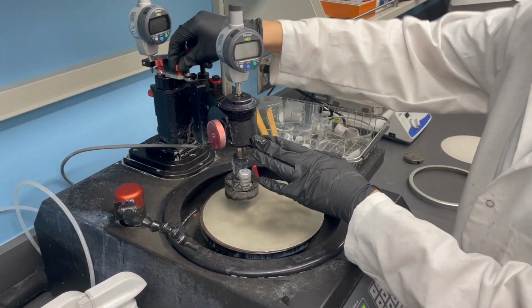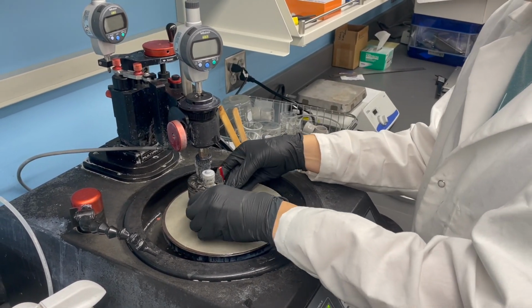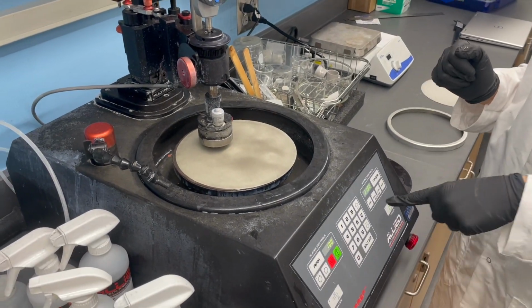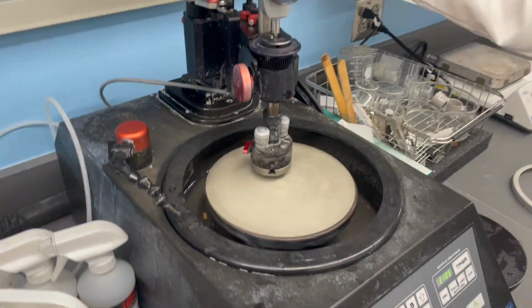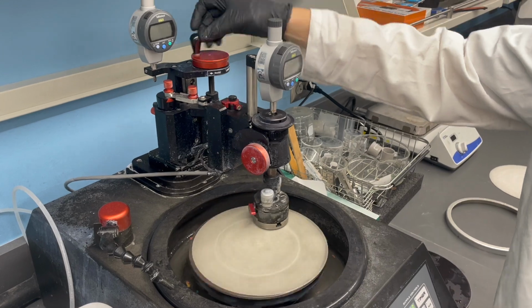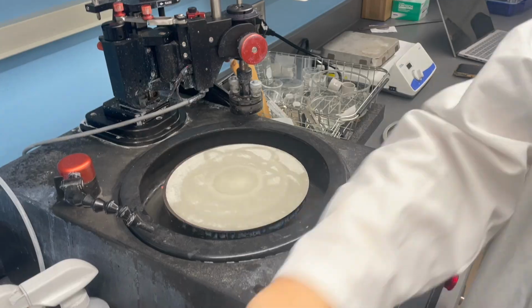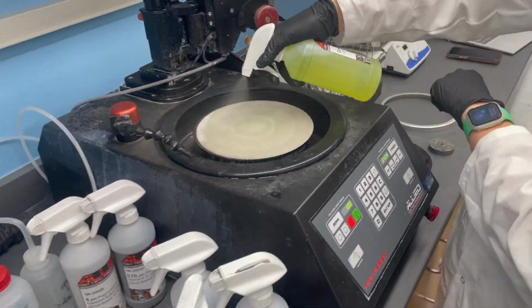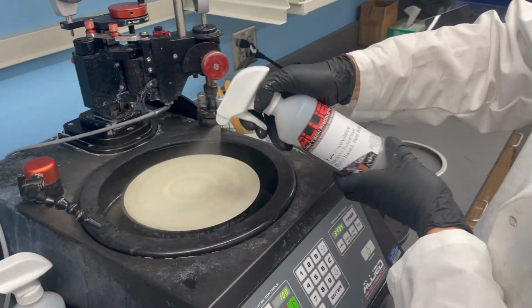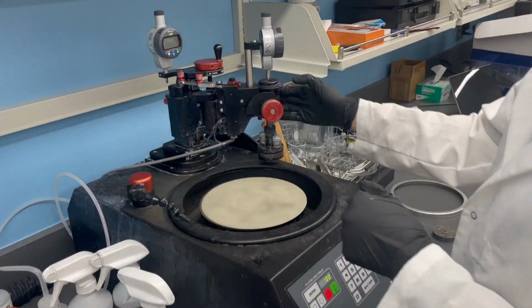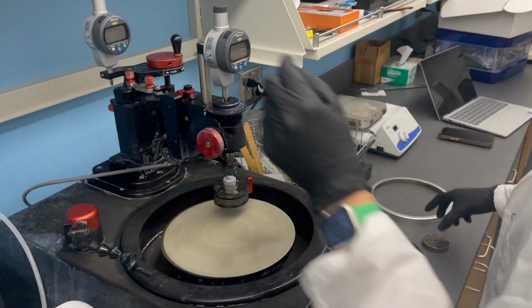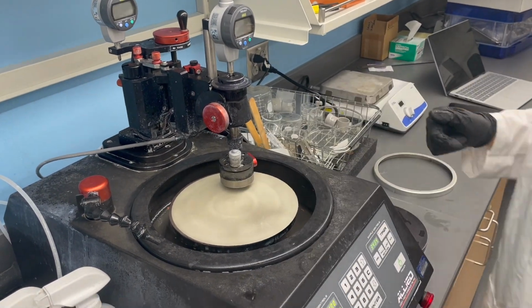Reattach the arm and secure the polishing fixture. Press the green button to start rotating the platen, then press both the oscillate and full buttons. Lower the arm until the sample makes contact. When you're finished, exchange the 3-micron polishing pad for the 1-micron polishing pad. Repeat the prior steps using the 1-micron diamond spray, reapplying the sprays approximately every 2 to 3 minutes.